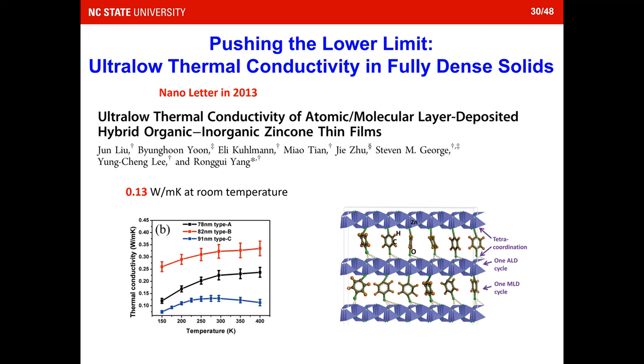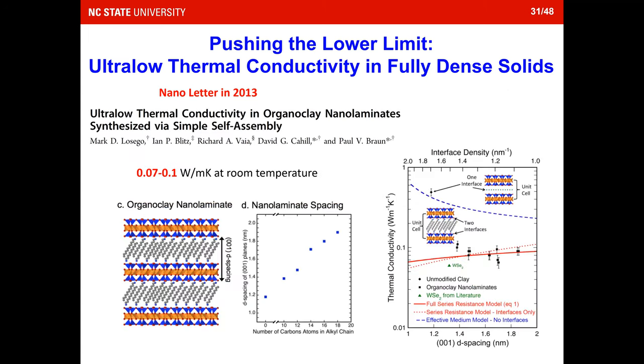the record. At the same year, Mark Losego, who is also an alumnus of our NC State, published another paper in Nano Letters. So they're able to tune the distance between those inorganic layers, right? And then they're trying to see whether they can push the limit even lower. So they're successful doing that because they control the spacing from 1.3 to 1.8, and the thermal conductivity is lower than what I get, 0.07 to 0.1.